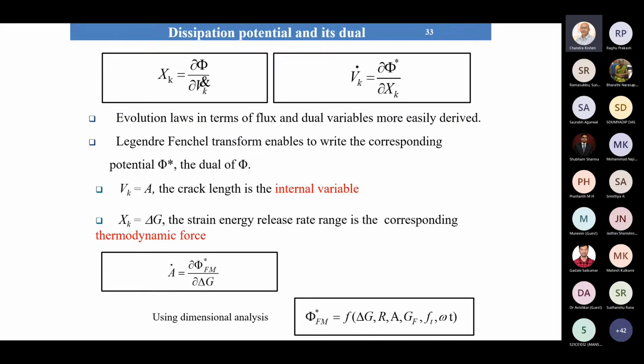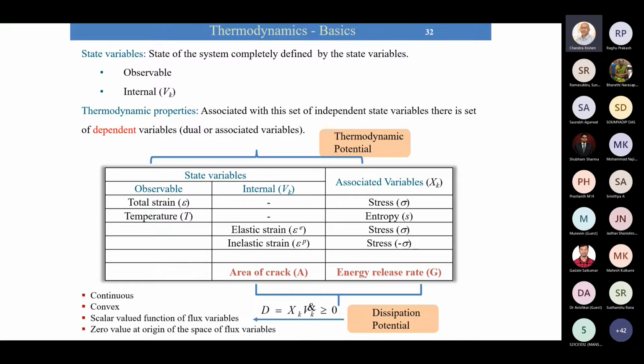Then, the best way to define the dissipative forces is to assume that there is a potential which exists, which is a sub-differentiable function of the internal flux. This phi is a potential. We want to establish a relationship between the associated variable and the internal variable. Here, to start with, we have done this using fracture mechanics and damage mechanics. For fracture mechanics, we have used the area of the crack or the length of the crack. We can assume, because the thickness is constant, as the thermodynamic force, and the crack is propagating due to the energy released. This is some kind of a force which we are applying.